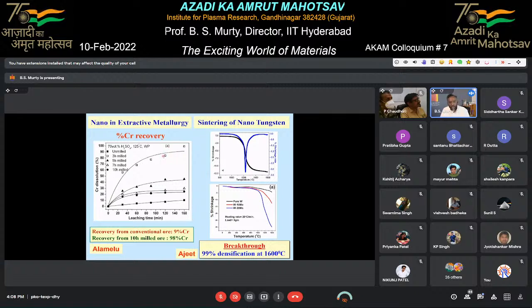Similarly, you can also recover metals from ores by making them nano. For example, we went to Orissa, Sukinda mines, and took chromite ore. Typically, when you recover chromium metal out of chromite ore, the recovery is less than 10%. We just ball milled for about 3 hours, and then you see the recovery goes to 90 to 95%. All this happens because a large surface area is created when you convert something into nano, and it immediately gives you very high reaction rates.